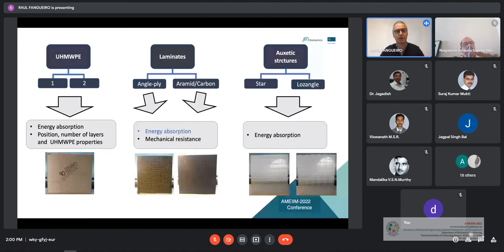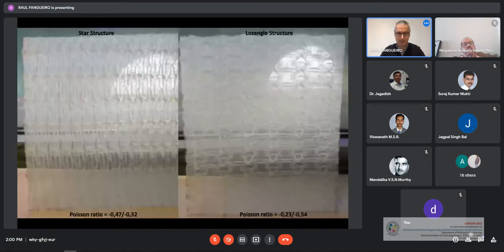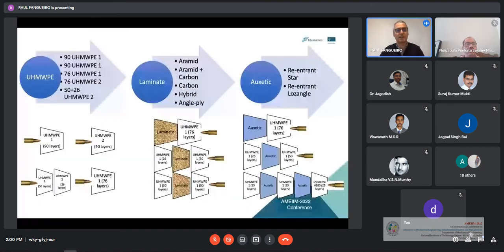So, these were the two materials we studied within this study, and we placed this auxetic material, the re-entrant and star and re-entrant lozenge, in several positions in terms of the number of layers we are using, one to stop the bullet and a second to improve the energy absorption.